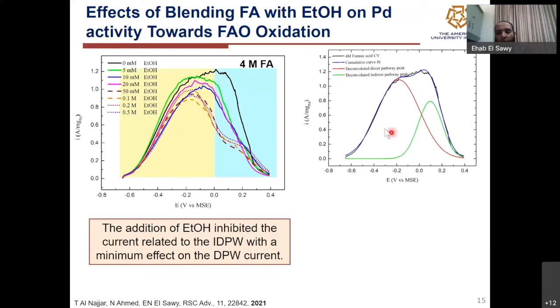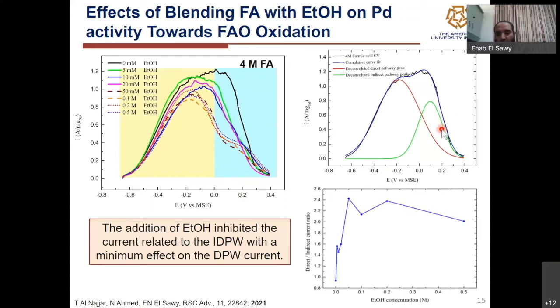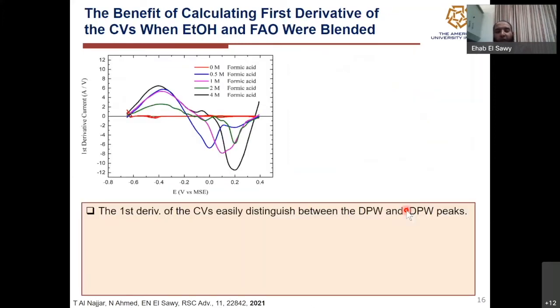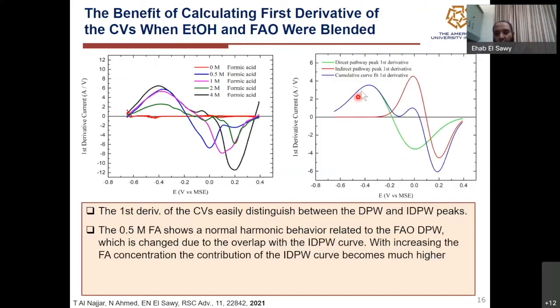Then we put this in quantitative terms by deconvoluting the peaks and comparing the direct and indirect peak currents. As you can see, with increasing ethanol concentration, we basically inhibited the indirect pathway. To look at this closer, we took the first derivative of the cyclic voltammetry. For the direct pathway we expect a harmonic shape, the green one, and for the indirect pathway it is the red one. When they overlap, they give something similar to the blue one.